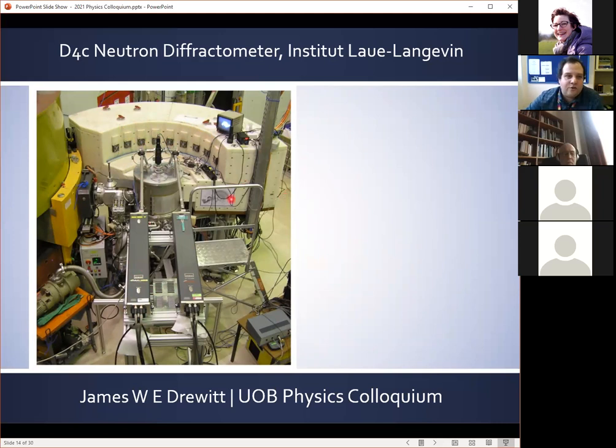Here we turn to neutron diffraction, and this is an example of our setup at the D4C neutron diffractometer at the Institut Laue-Langevin. We have a similar setup to X-rays. Neutrons come into the sample, which is levitated here inside the instrument bell jar, and it's heated from these two lasers from above. Except instead of a two-dimensional detector array, we detect the scattered neutrons using this array of detectors at fixed scattering angle. In fact, this entire detector bank is on these air cushions and moves during the experiment to make sure there are no gaps in measured scattering angle.